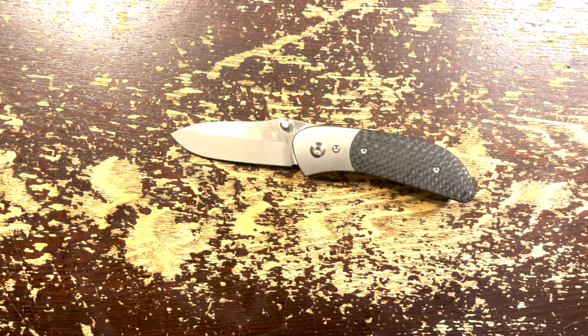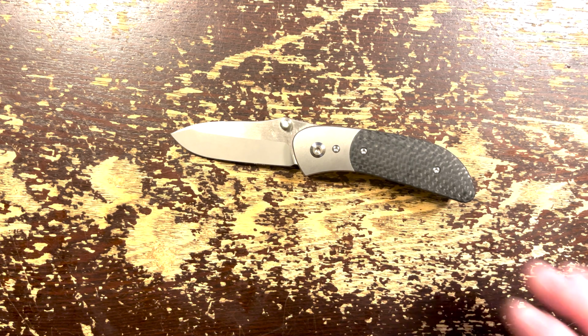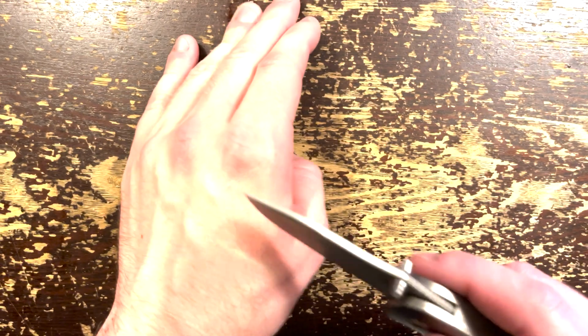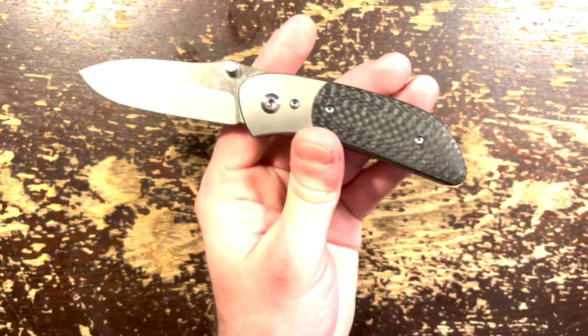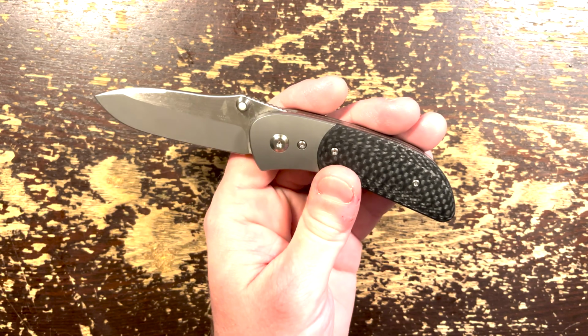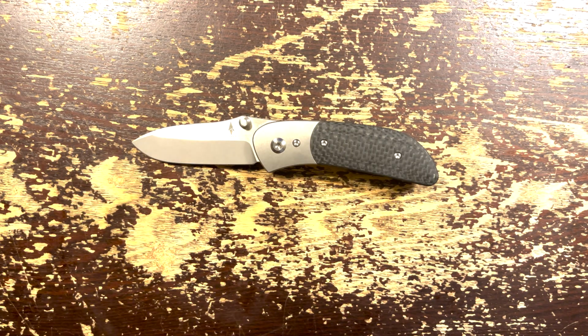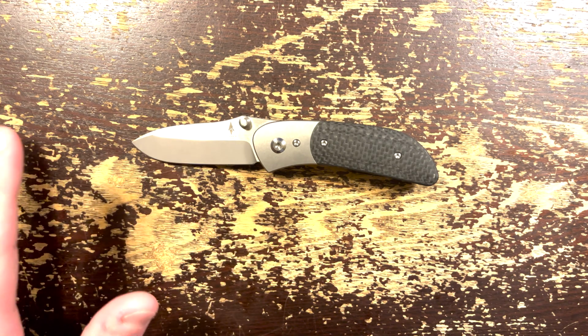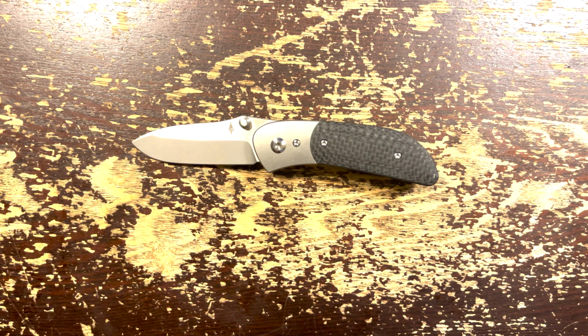After a few weeks of use cutting normally, I would feel the blade was too dull to be useful, and then I would apply a bit of a sawing motion and the blade would start cutting again. Even right now, when the blade is so dull that I couldn't cut myself with it, if I wanted to, I can still use that sawing motion to cut through some small things if I needed to. That's wild. And after a month or so, just as quickly as it got to the working edge, it went from that edge to totally dull in different spots based on how much I'd used those particular places.